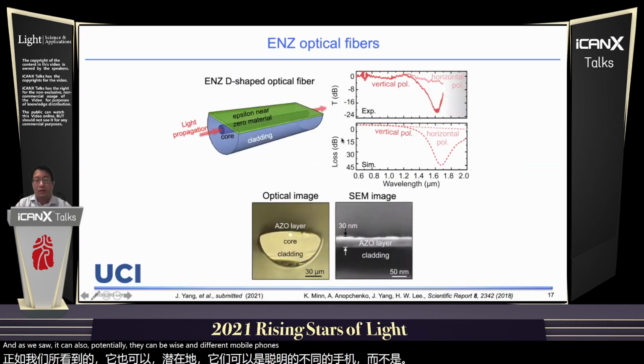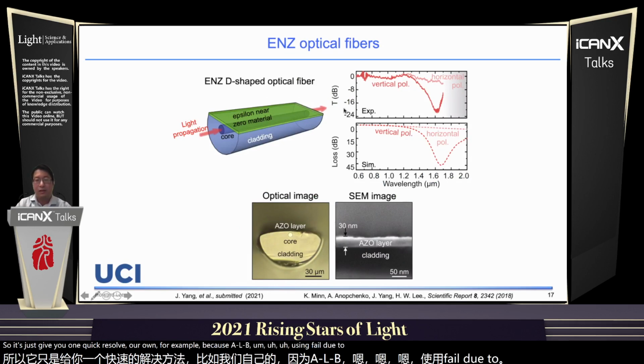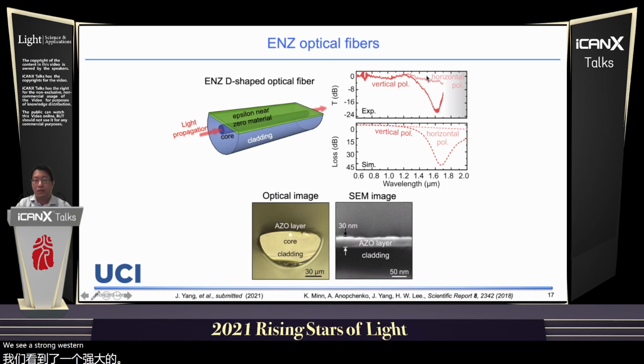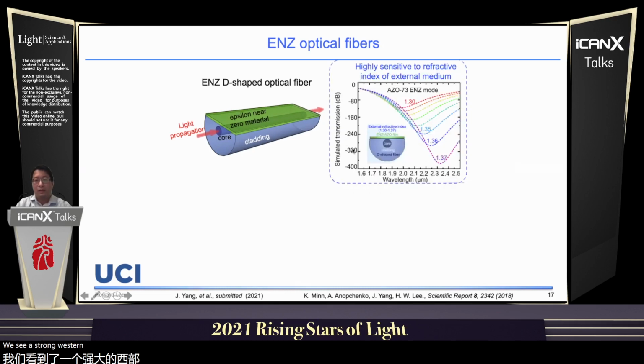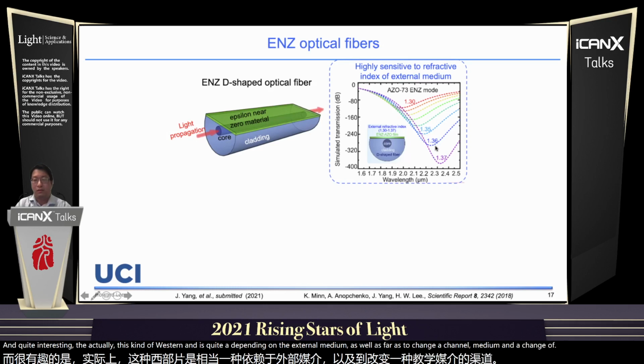To give you one quick result, for example, we coat AZO using ALD on the D-shaped fiber, and we see a strong resonance here, which corresponds to ENZ mode excitation. We also confirm we can have high field confinement here. Quite interestingly, this resonance depends strongly on the external medium as well. If you change the external medium, you can change the resonance quite significantly, so you can potentially use it as an ultra-sensitive sensor.